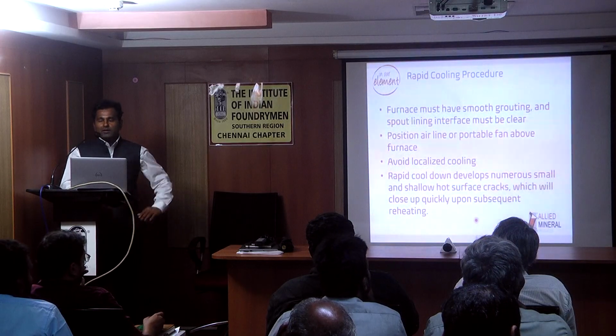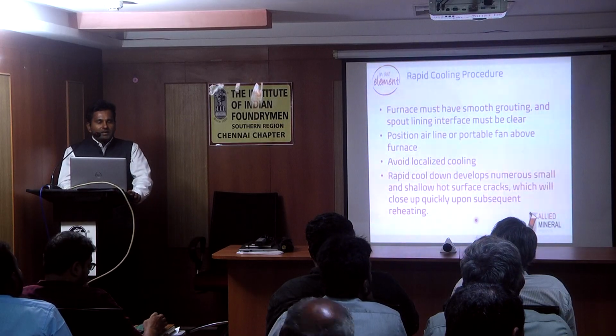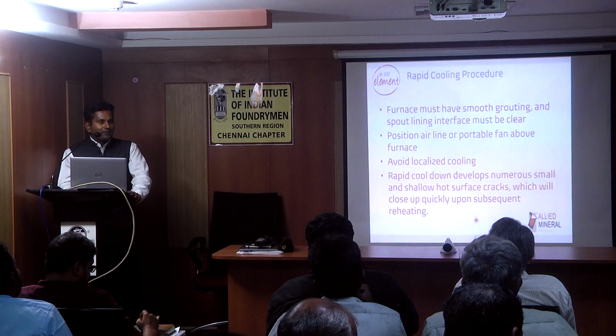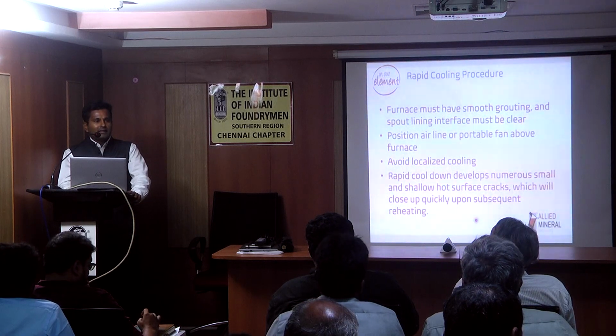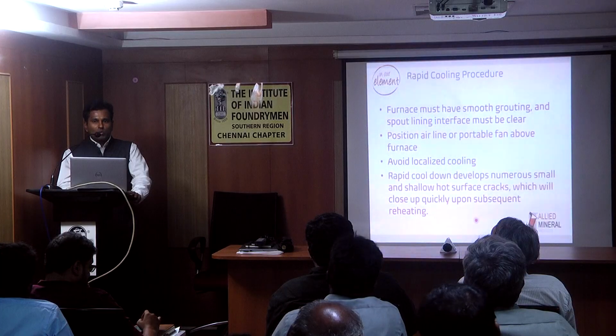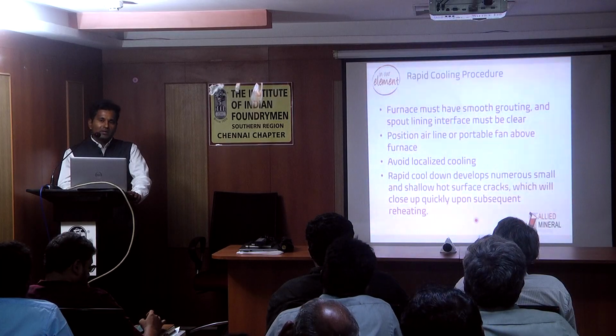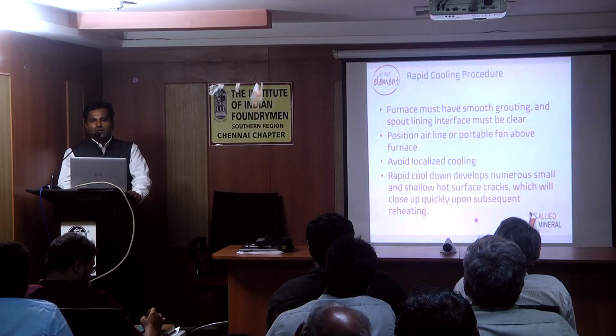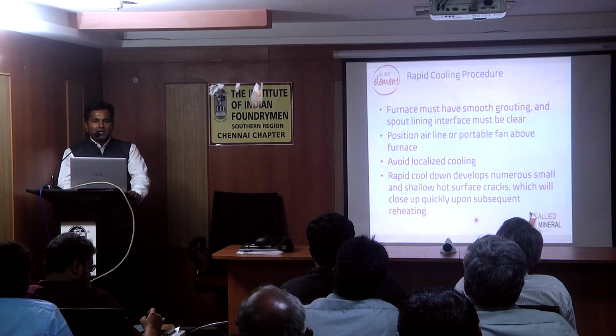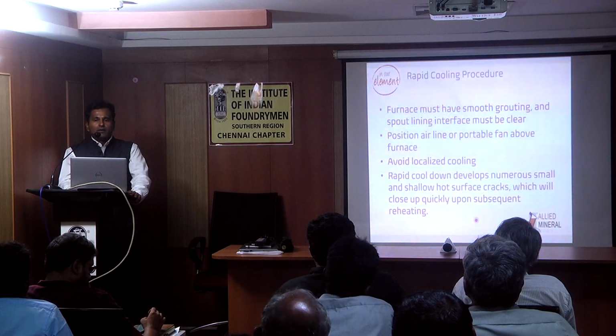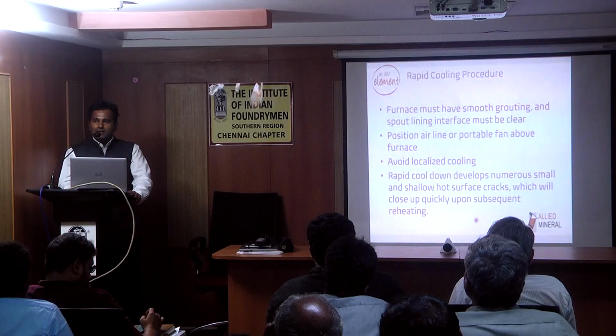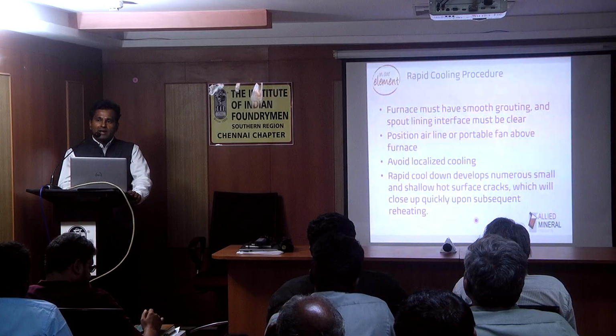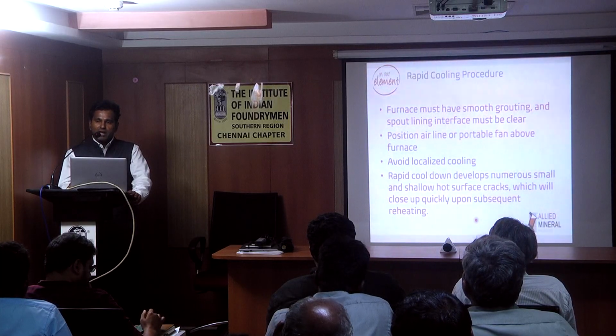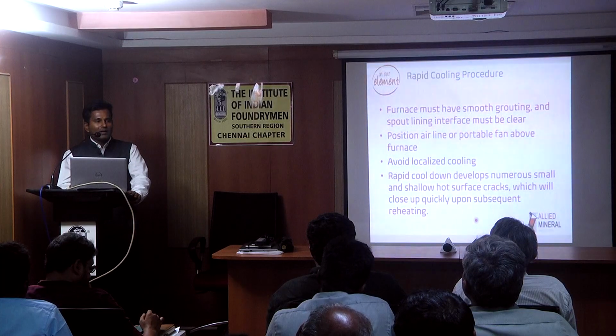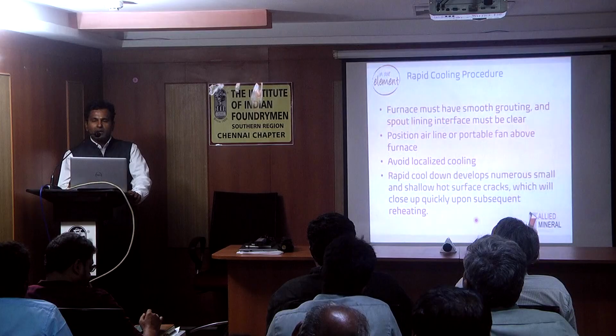So, rapid cooling. Generally people used to have a different school of thought. They think that if cooling is slow, thermal shock is less, so they will have a better lining life. But we recommend rapid cooling. When you do rapid cooling, there will be many cracks, but the cracks are not deep enough. They are very shallow. When you do a proper rapid cold start again, these shallow cracks will seal automatically with lesser heat.